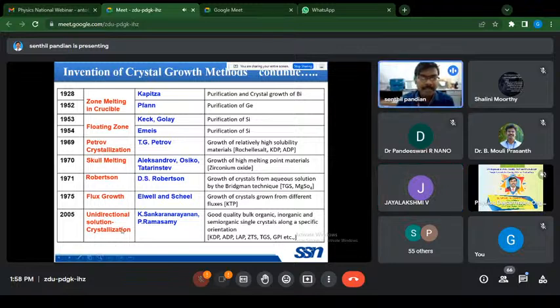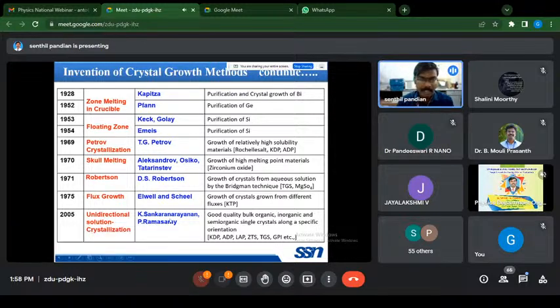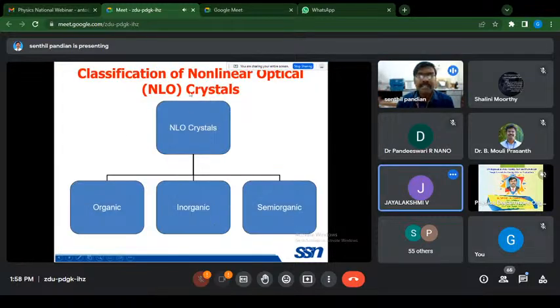So far, by this method, more than 200 crystals have been grown. We are able to grow low soluble material, moderately soluble material, positive soluble, and negative soluble. All kinds of crystals can be grown by this Sankaranarayanan-Ramasamy method. And these are the classifications of nonlinear optical single crystals. So one can grow organic single crystals by this SR method.